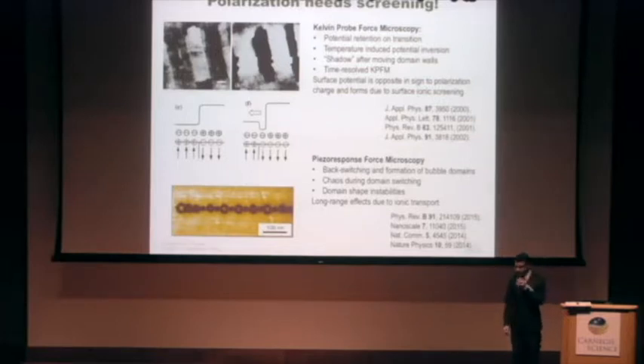And so over the last two decades or so, we have a number of experiments, from Kelvin probe force microscopy, to try to understand surface charge dynamics in ferroelectric thin films and ferroelectric single crystals. And you can see some quite interesting results that have been shown. For example, you can take barium titanate or other materials above their TC, and you can see how the surface charges invert. You can see shadows after a moving domain wall.